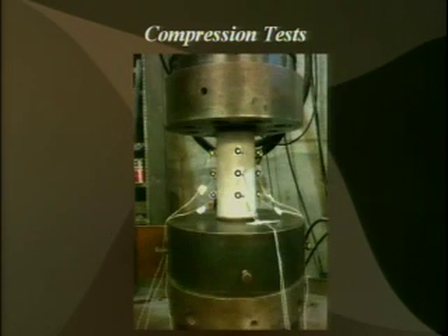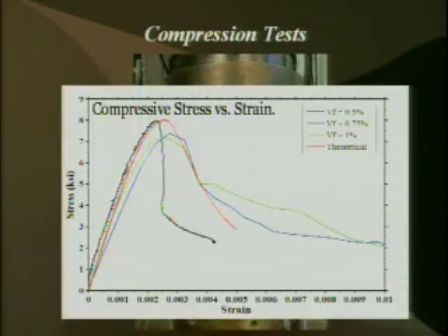The first test that we did were the compression tests. From each batch, 2 cylinders having a diameter of 4 inches and a height of 8 inches were tested under compression. In order to measure the cylinder's displacement, sensors were located along the cylinder length over a 270 arc, as we can see in the picture. The results show that even though the compressive strength is not substantially affected by the quantity of fibers in the mixture, the compression ductility increases with an increase in the amount of steel fibers.